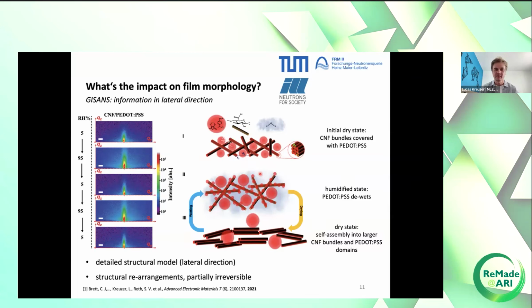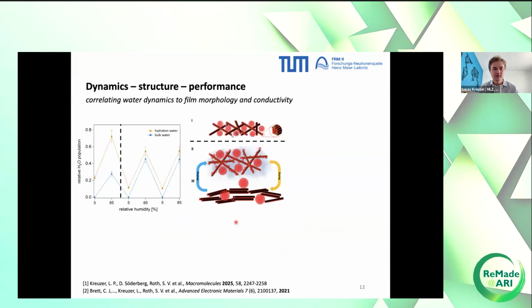Basically, GISANS gives us a very detailed structural model in lateral direction. And what we see here is that we have quite significant structural rearrangements that are partially irreversible. So after a first humidification step, we enter a different morphological loop. So something happens during this first humidification step. And this is something we also saw with the QENS data, where the first cycle somehow differs from the subsequent 2 cycles. So I draw a line here, and we could draw the line after or just before the first humidification step.